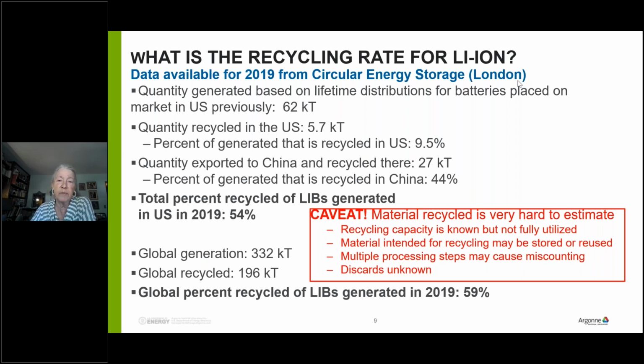So what Circular Energy Storage, who's one of our collaborators on this work, has shown from the best data that can be obtained is that, in fact, for the US, something like half of the batteries actually are getting recycled. About 10% of them are getting recycled, that is shredded, in the US, and then the material is exported. And the rest, about 40%, is actually being recycled in China. Globally, the number is something like 60% of batteries actually getting recycled. But there's a big red caveat on these results because it's extremely difficult to get the data, and there's a lot of uncertainty in it, but the point is that there's actually a lot of material already getting recycled.